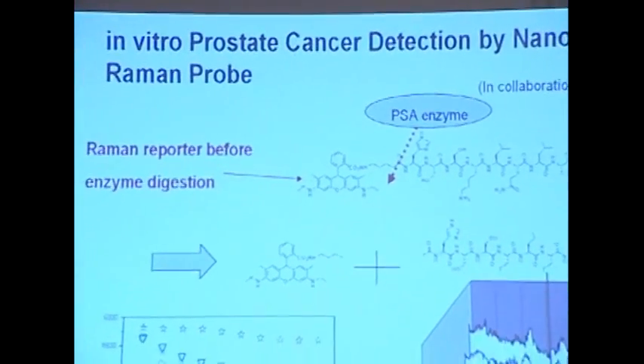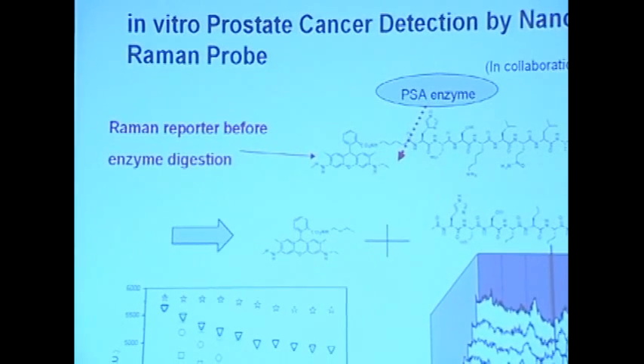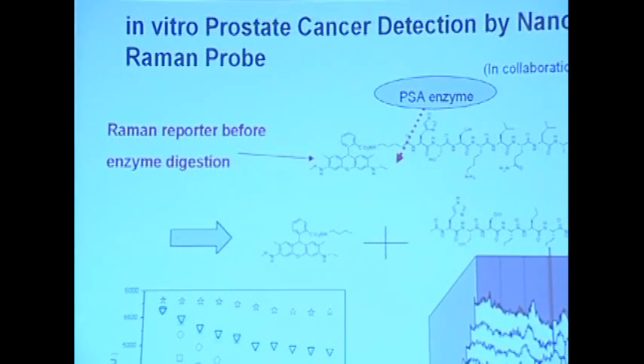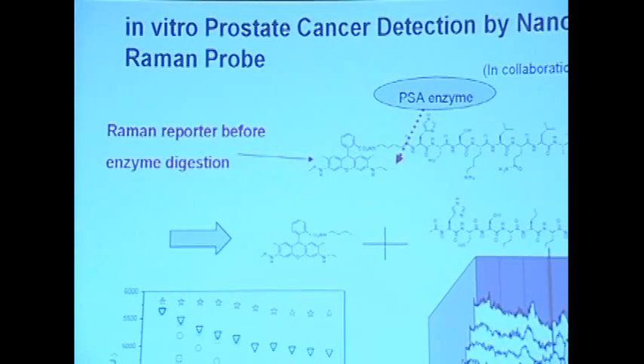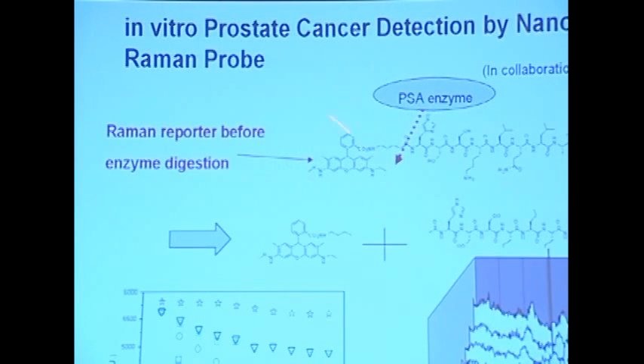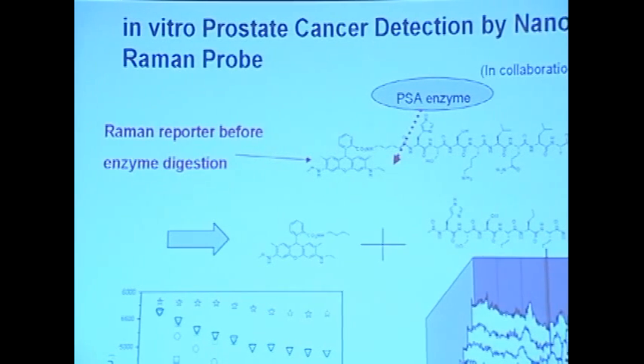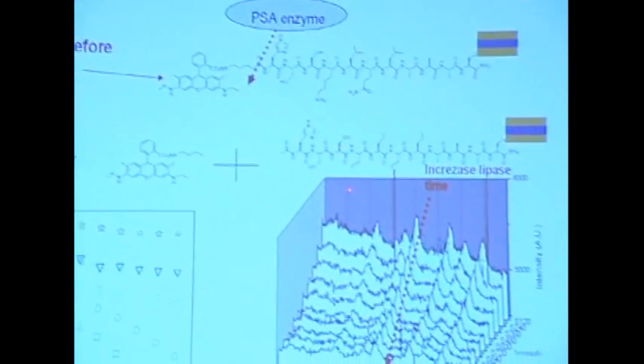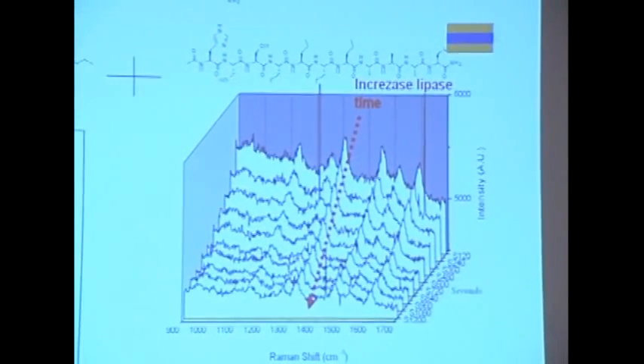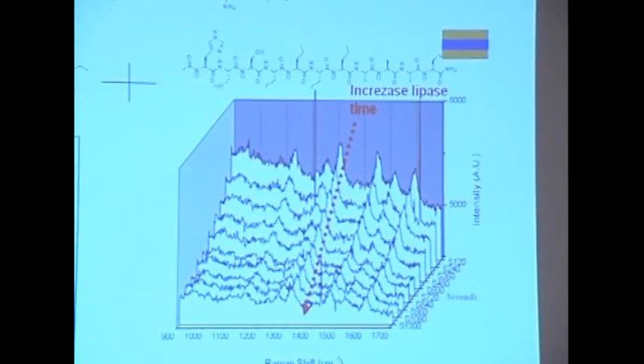Now, I didn't show the simulation result. The field around this resonator is extremely strong, about 10 nanometers around this nanoresonator. After that, it decays dramatically. So if the reporter drifts 10 nanometers away, you don't see it. So once we see the signal drop, we know there is an enzyme that comes in, specifically reacts with this bond, and removes the reporter.